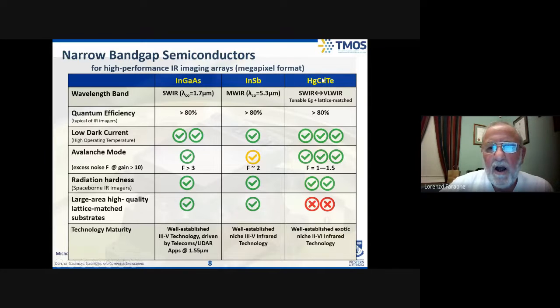In order to reduce that noise, I usually have to cool detectors in the long wave infrared to around 80 Kelvin, in the midwave infrared to around 150 Kelvin, and in the shortwave infrared they can operate at room temperature. So the technology gets more difficult as I go from shortwave to midwave to long wave, and the operating temperature, in order to get a decent signal to noise ratio, I have to cool further and further as I go to longer wavelengths.